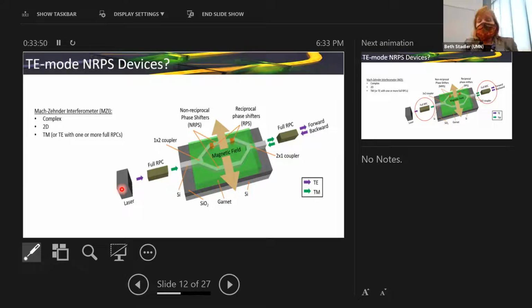Yeah. So if they only work for TM, that means you also need to have the 220 nanometer thickness usually to get the best, or you need a longer device to get the best interaction between the TM mode and the garnet. You have to have a pretty thin film. You need a full reciprocal polarization converter on both ends, because you go from TE to TM before your interferometer, and then another full reciprocal, really it's mode converter to get TE again back into your system, and then the same thing coming back.